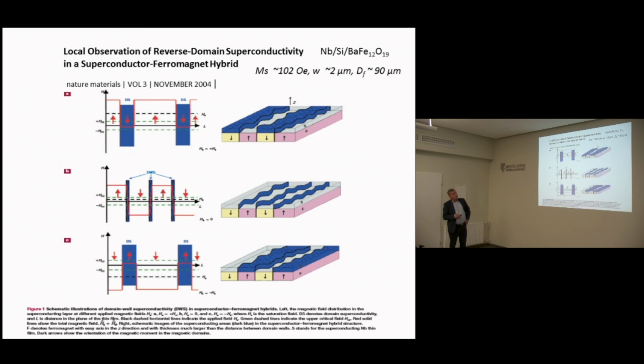However, how did they do this? First, a single crystal with a thickness of about 90 microns was cut. Then, in order to avoid the proximity effect, as I mentioned earlier, they deposited 10 nanometers of silicon and then 60 nanometers of niobium. Generally, the domain wall width is very large, about 2 microns, whereas in the Aladeshkin model they assume that the domain walls are 0. So the idea of the paper was to observe superconductivity in such a heterostructure.